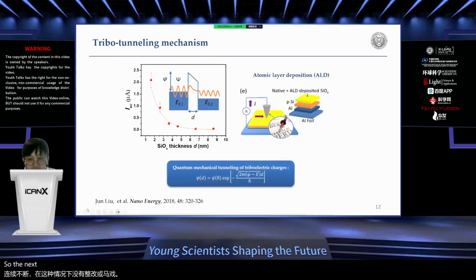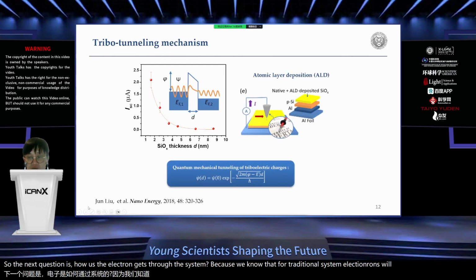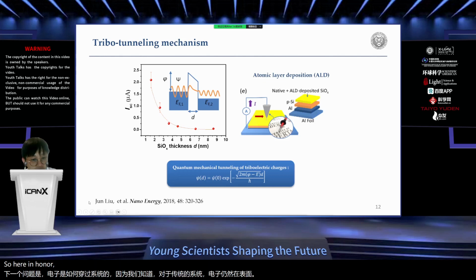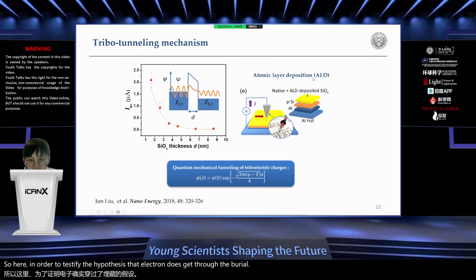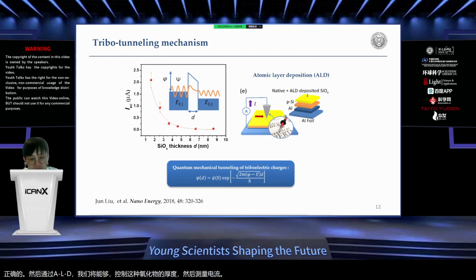So the next question is, how do the electrons get through the system, right? Because we know that for a traditional system, electrons will just stay on the surface. So here, in order to test the hypothesis that electrons do get through the barrier, we did atomic layer deposition of oxide on the silicon, because we know that any silicon has a native oxide thickness of around 1 to 2 nanometers as long as it's exposed to the atmosphere, right? And then by using ALD, we are able to control the thickness of this oxide and measure the output current simultaneously, right?